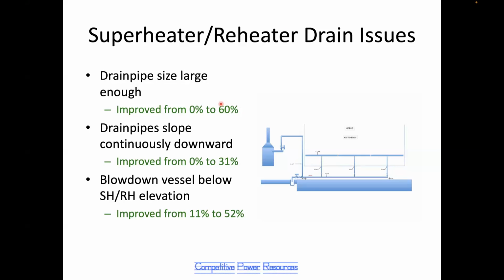When there's no pressure in the boiler on a cold start, the water can only move by gravity and must flow downhill in order to be removed from the superheater. So if the drain pipes do not slope continuously downhill, if instead they go up and down, as this cartoon shows, up to the blowdown tank here, the water cannot move out, no matter what you do with the valves. In 2008, none of the drain pipes had a continuous downward slope. Now about 1/3 of them do, so there's some improvement there.